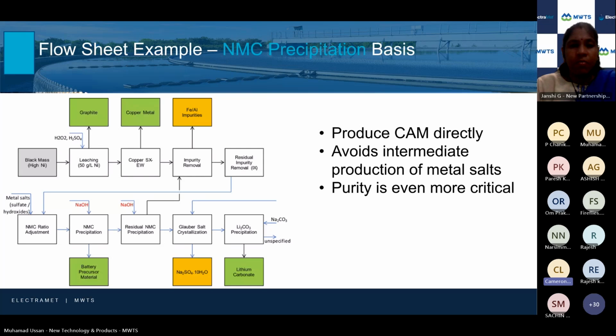Okay, so that was making all the different metal salts. So here's an example flow sheet of going straight to the cathode active material process. It looks very similar, right? You still have the copper removal and impurity removal. The only difference is instead of a solvent extraction step for cobalt, a different one for nickel, a different one for lithium, they're now taking that purified leachate once you remove the copper and trying to make the cathode material directly from there. So you do chemistry on this, what's called an NMC solution. You add in a variety of chemicals, and it produces your cathode active material.